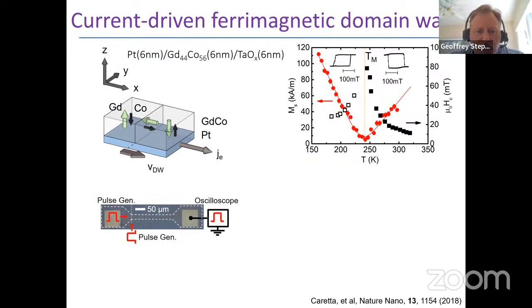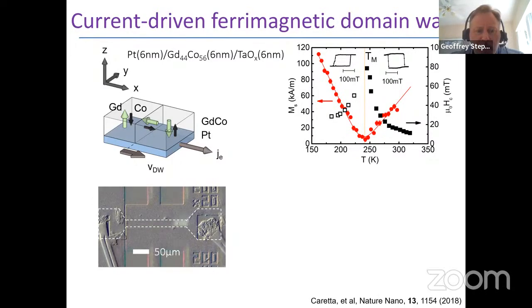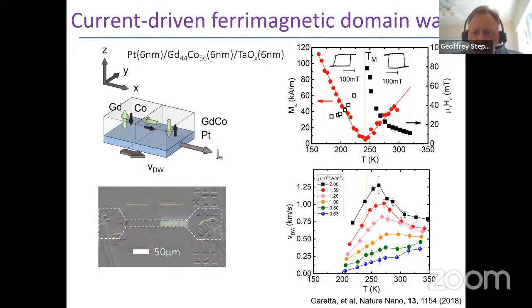And so we've done this using MOKE, where we can drive a magnetic domain wall along a track and track the velocity as a function of the degree of compensation. And we found, exactly as one would expect, that when you are away from compensation, the maximum velocity for the magnetic domain wall is relatively low, on the order of hundreds of meters per second. But there is a temperature at which the velocity becomes very large, in excess of a kilometer per second. But that temperature does not correspond to the magnetic compensation temperature. It corresponds instead to the angular momentum compensation temperature. So in a rare earth transition metal alloy, the cobalt here and the gadolinium have different g factors.